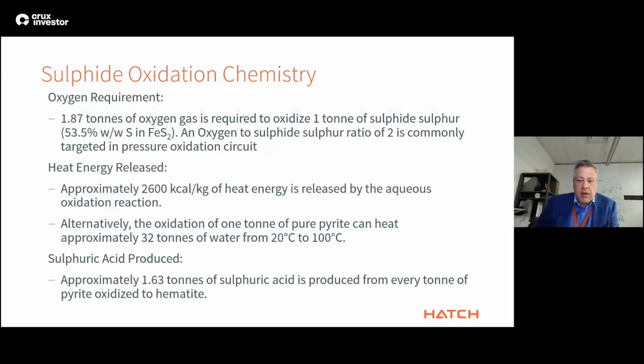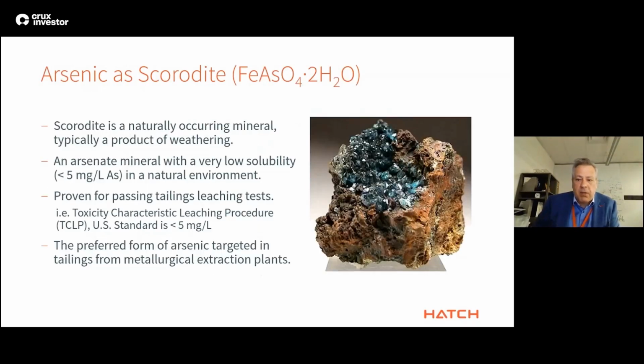The acid produced by the oxidation of sulfide sulfur must be neutralized by the addition of lime and limestone, unless it can be consumed elsewhere, for example, in the leaching of copper-bearing minerals such as copper oxide, or in the leaching of zinc. Scorodite is a naturally occurring arsenate mineral with a very low solubility in a natural environment. Crystalline scorodite, which is produced at elevated temperatures, has been found to be more chemically stable than low-temperature products and has been proven to pass tailings leachate toxicity tests with less than 5 milligrams per liter of leachable arsenic. It is therefore the preferred form of arsenic in tailings residues produced by metallurgical extraction plants.